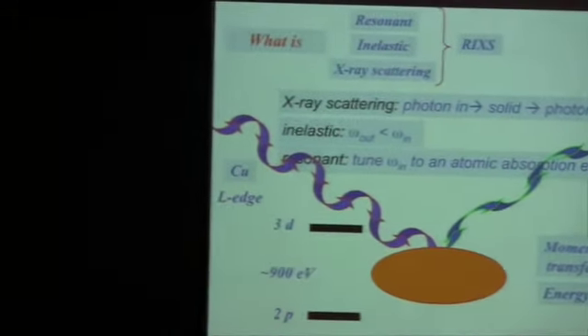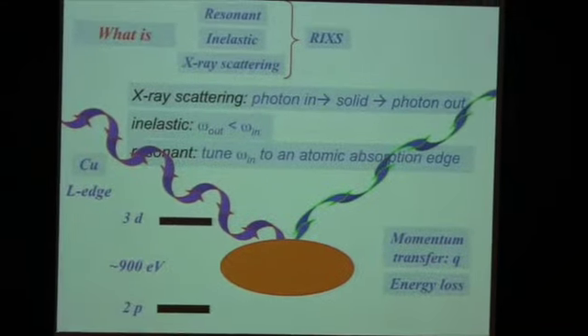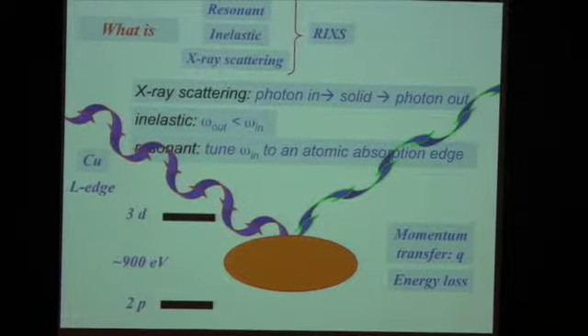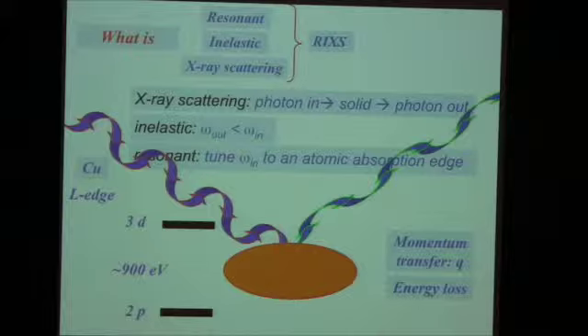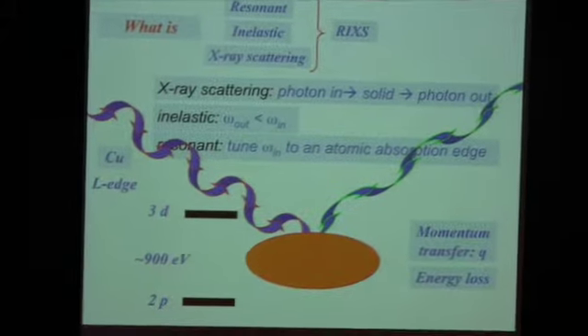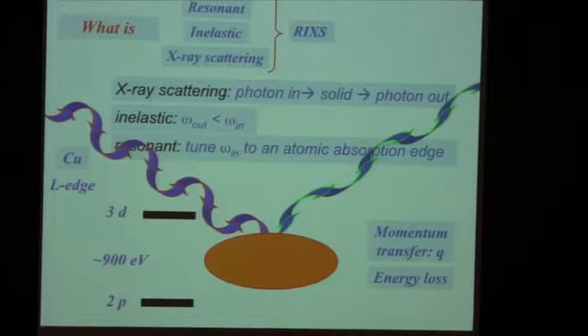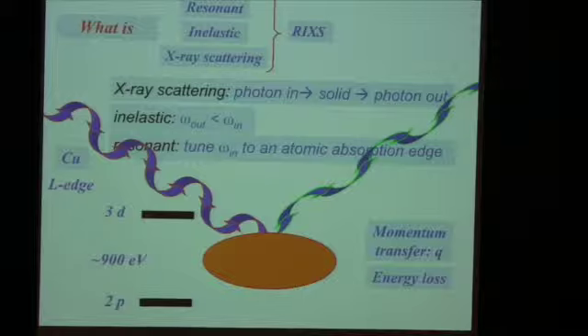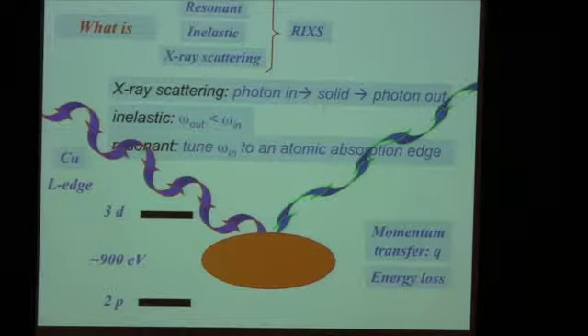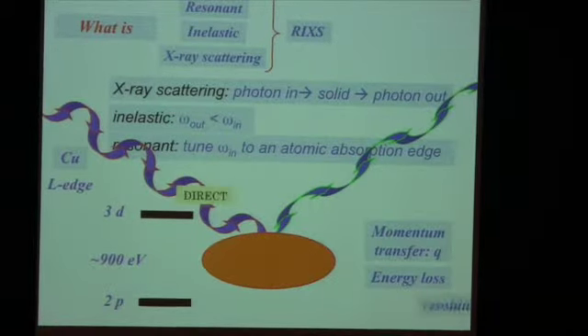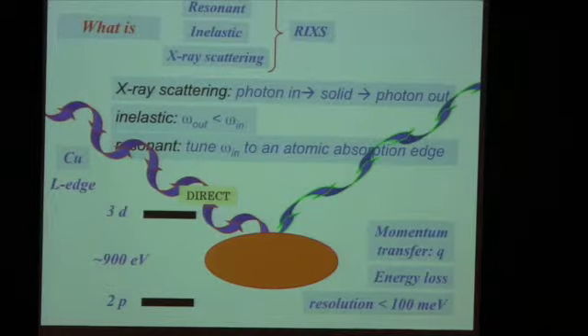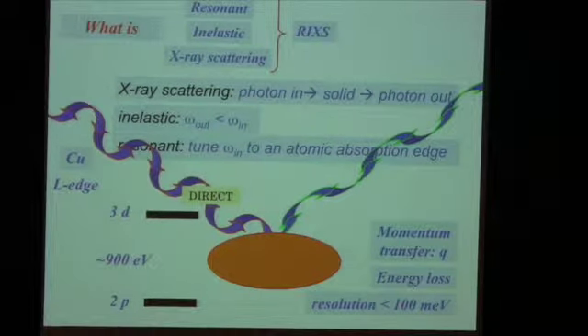So by copper L-edge RIXS, you put the electron out of the 2p core into the 3d state. It sits there for a while, and then a d electron decays, emitting an X-ray photon that has lost energy, and that energy has been transferred to the 3d electrons of the system. And this is called direct RIXS because you directly probe the valence electrons.